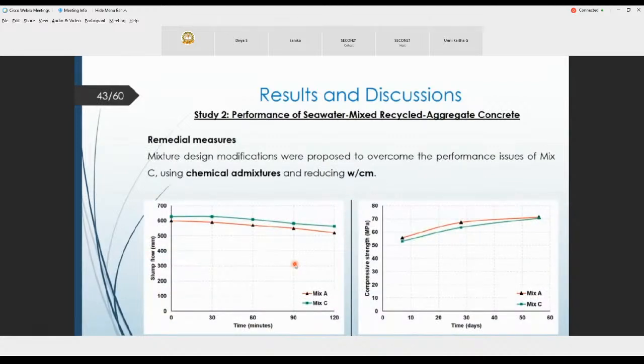Although most measures favor using recycled aggregate concrete, remedial measures can still be done to improve the performance of mix C. Mixture design modifications were proposed to overcome performance issues using chemical admixtures and reducing water-cement ratio, as seen in the slump flow and compressive strength measurements. It's not perfect, but with these remedial measures, we still find these results attractive for using RCA.